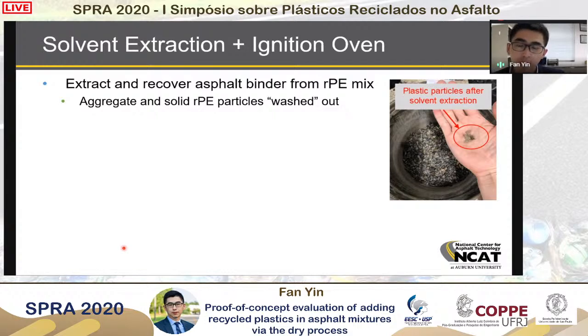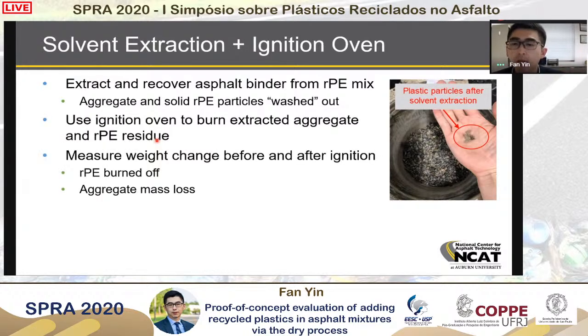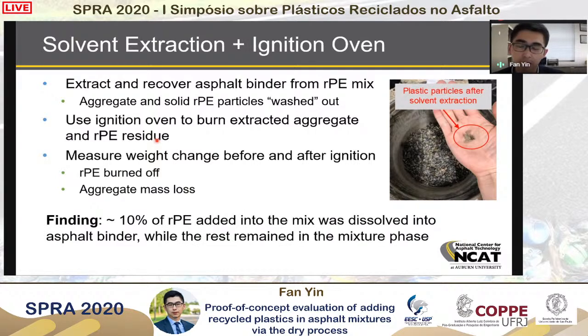So the first thing we do is the extraction and recovery. In that case, all the plastic particles that stay in the solid phase are going to be washed out by the solvent together with the aggregate. Then we can use the ignition oven to burn the extracted aggregate and the plastic residue, and measure the weight change before and after. Based on that, we can estimate how much plastic goes into the binder and how much stays outside the binder.